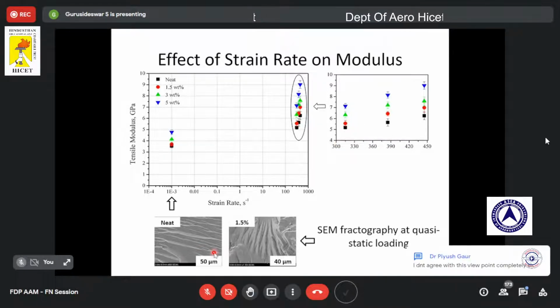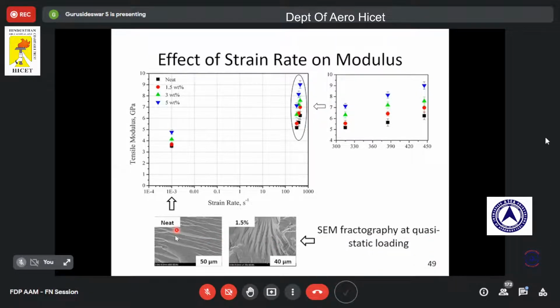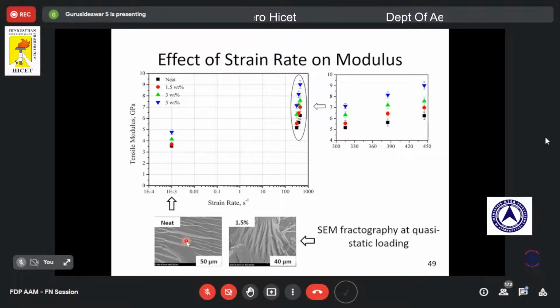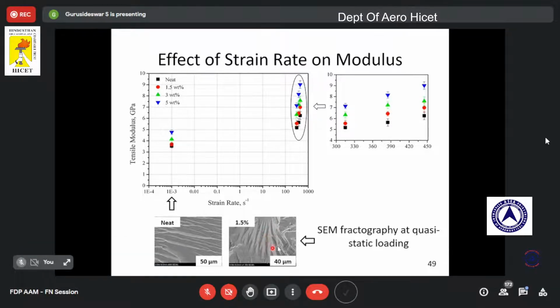And this figure shows the scanning electron microscope photography at quasi-static loading. So this is for the neat sample. We can see a featureless image, the river-like pattern, which we observe for a brittle failure. And this is for 1.5% clay. You can see there is agglomeration, and also the roughness has increased, which shows that the brittleness has increased. So this is what we observe from this micrograph.